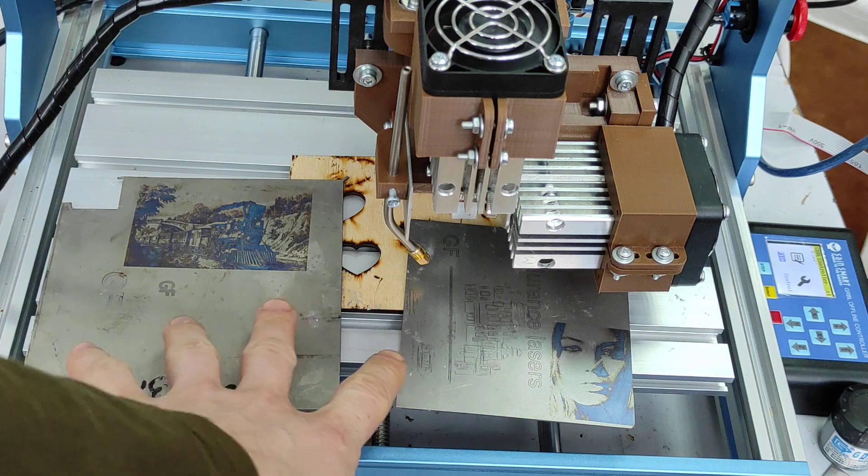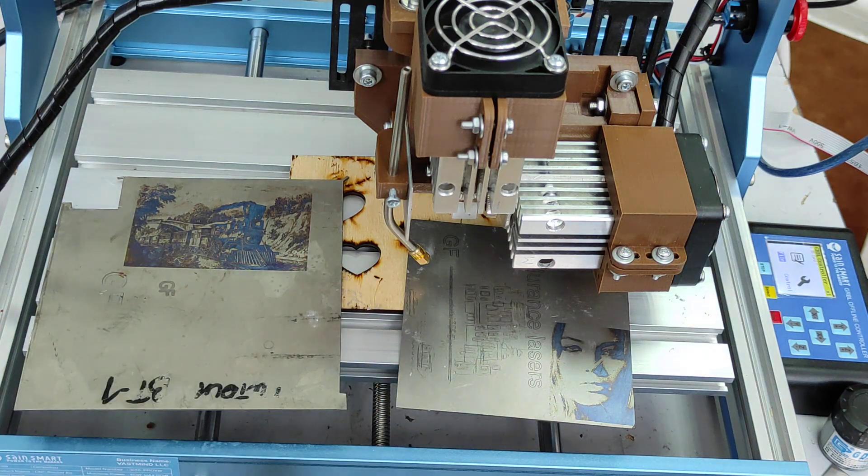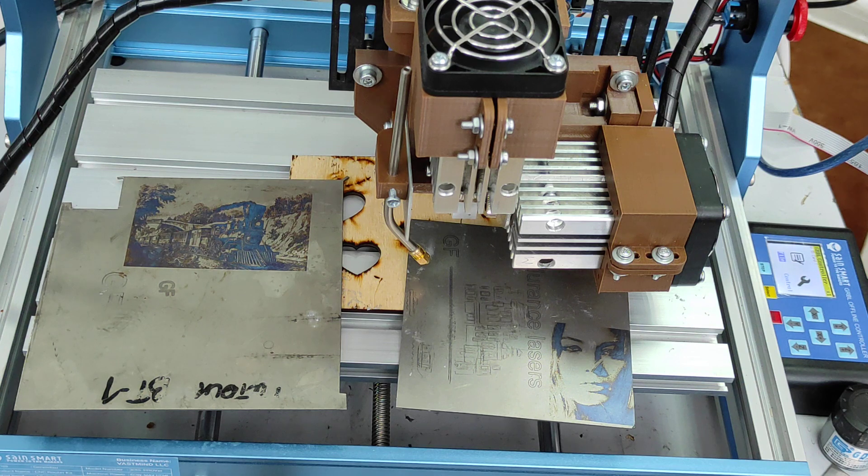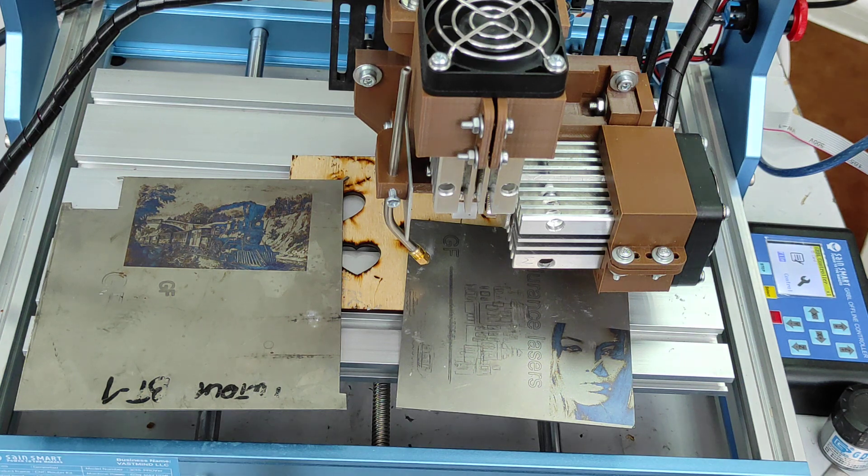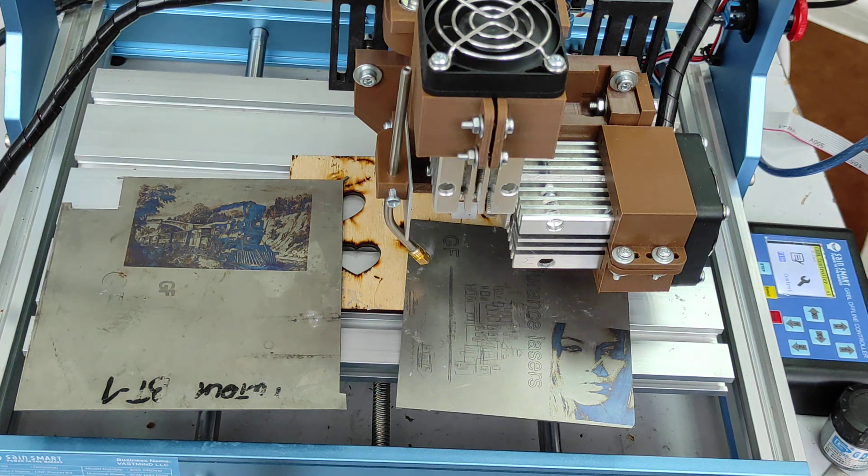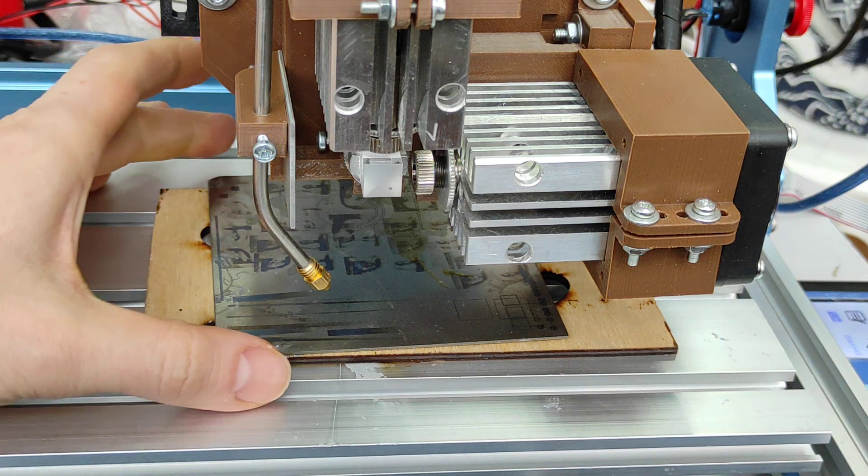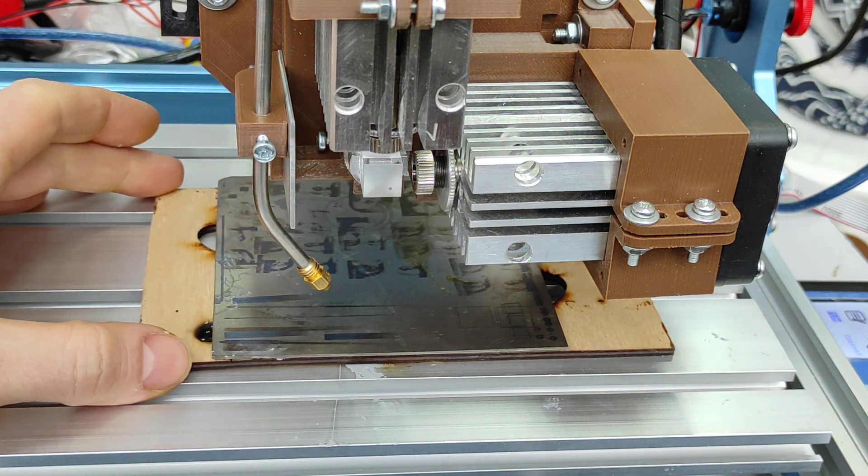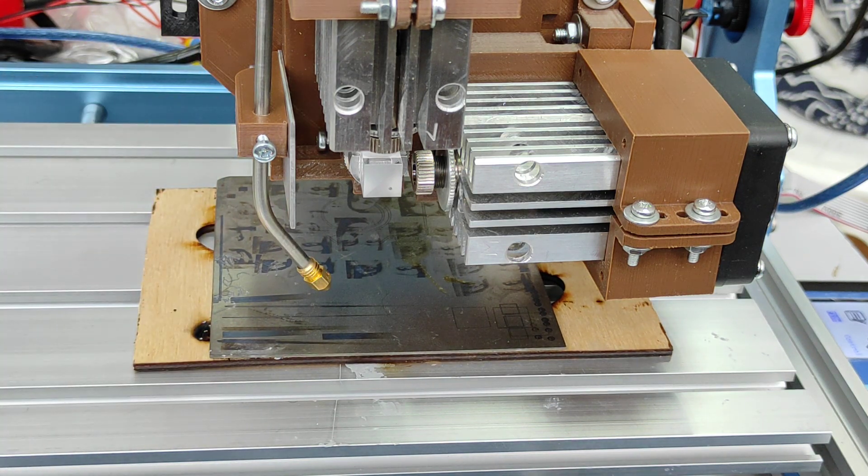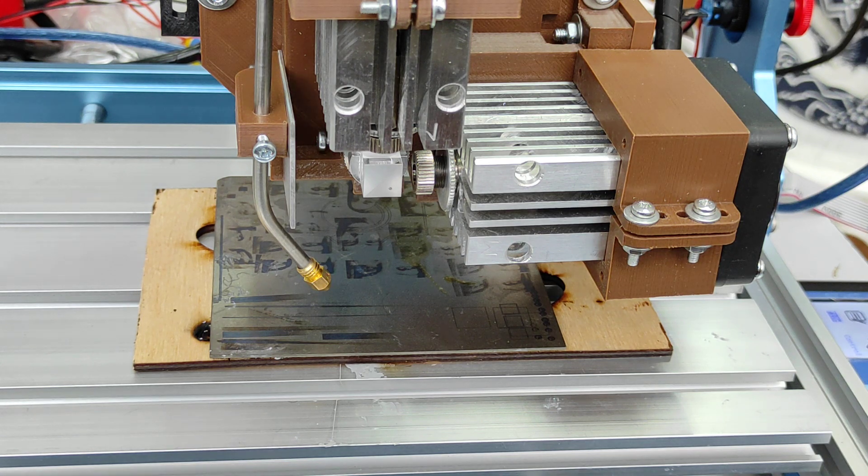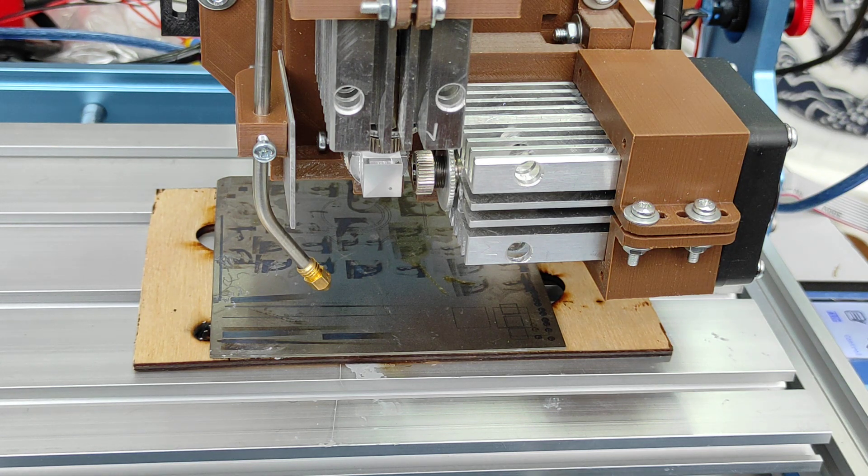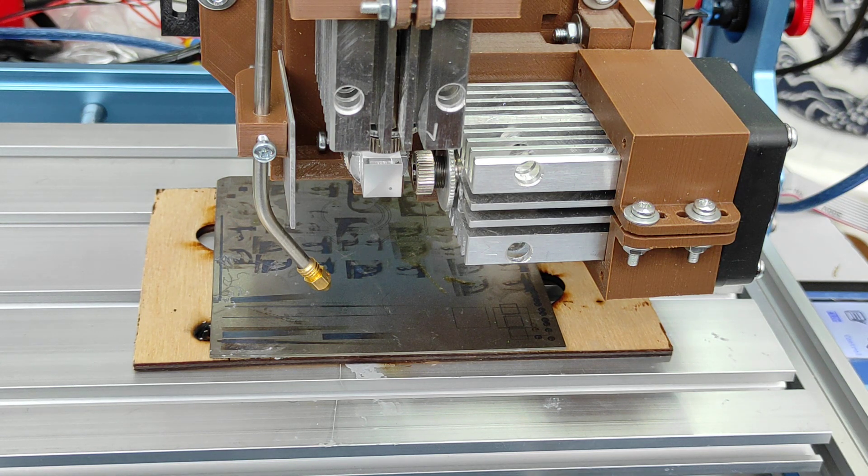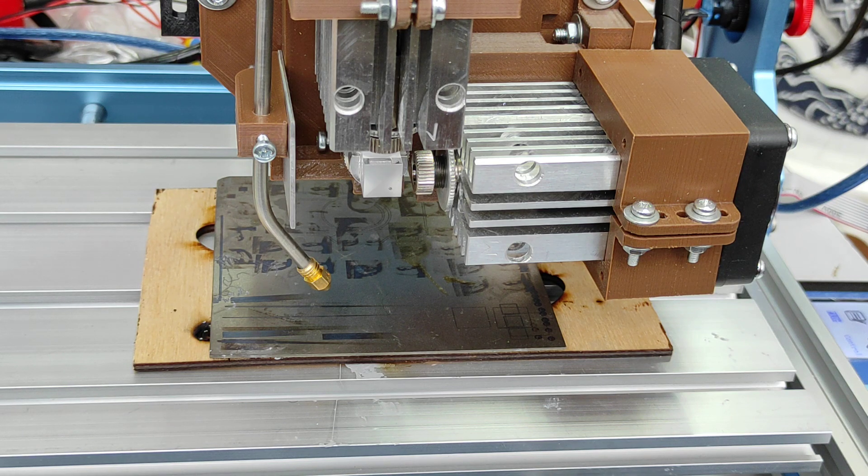Let's try two different titanium plates. The engraving speed will be 500 millimeters per minute and 99 percent power. I already put this on our worktop. Keep in mind that to have a very good and accurate engraving you have to be in focus.